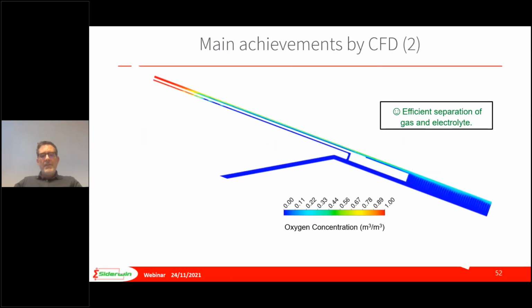And then the third achievement was to properly remove the gas from the electrolyte in this degassing device on the top of the cell. As you can see on the picture, which is representing the oxygen concentration in the cell, we start here in the electrolyte with an oxygen concentration close to 0. We have generation of bubbles in the anode here. And then the mix of electrolyte and gas is coming up. We have the separation. And then here in this area, we have only pure oxygen that could be removed from the cell. So at the end of this iterative process between buildings and between CFD simulations, we were able to define what we think to be a very efficient cell.